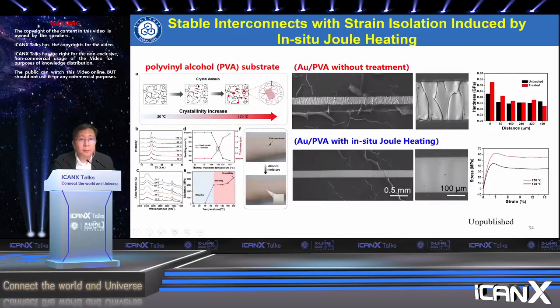And also, we can make the stable interconnect with strain isolation induced by the in situ joule heating method, especially for some very soft substrate, for example, this PVA substrate. Here you can see that the gold electrode on the PVA substrate without treatment will easily detach and break. After the in situ joule heating method, benefiting from the precise control of the heating location around the electrode, the crystallization and enhanced rigidity of the PVA is restricted to the desired areas, which leads to the effective strain isolation.